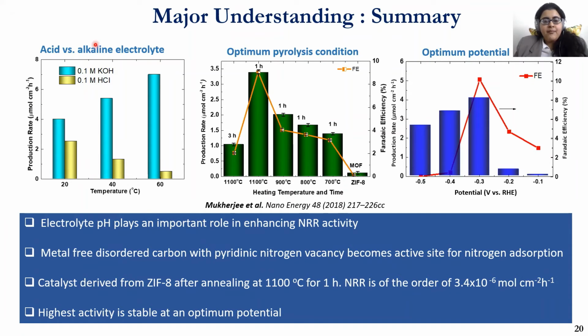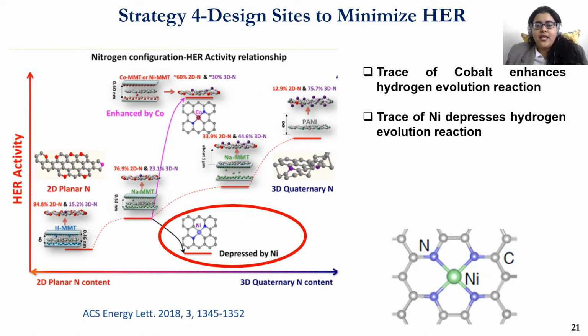But our major understanding was that we optimized the electrolyte. We used acid versus alkaline electrolyte and compared the production rate. We optimized the pyrolysis condition and compared the production rate. We optimized the Faradaic efficiency. We optimized the potential and found the optimum potential for which we can get the maximum Faradaic efficiency. So now it's important to see how the selectivity can be further increased.